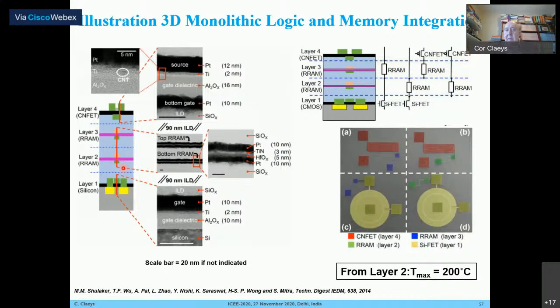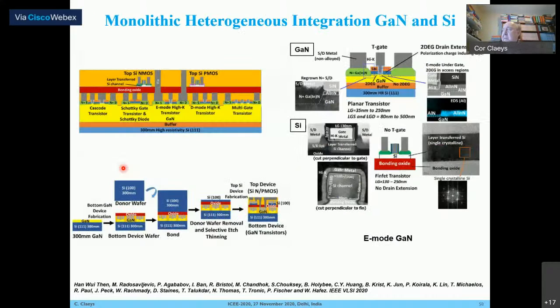And finally, that's my last example, published very recently, presented at the VLSI conference in June, is work coming from Intel, using gallium nitride on silicon, because that's always the basis, starting with silicon. Processing gallium nitride on silicon, they have been making an enhancement mode gallium nitride transistor. Then they used a second wafer and did wafer bonding. And then they processed silicon devices in the top layer. In that way, you got a very special type of devices, a combination of gallium nitride devices, where you can have high frequency and high power, combined with silicon devices. And in my opinion, that's opening a totally new range of different applications.